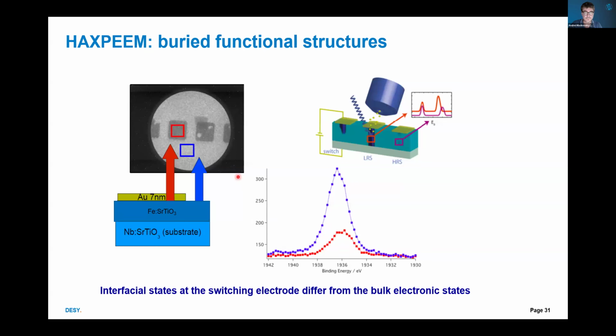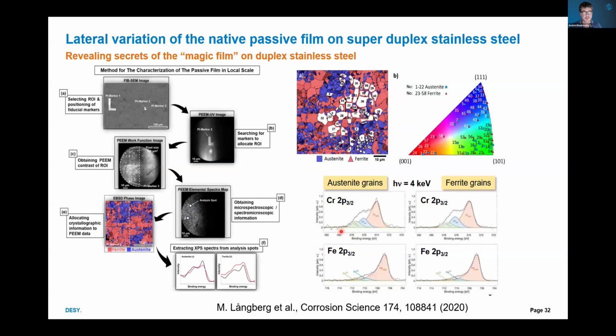Or you can also study ferroelectrics. You can see the pads clearly, and if there is an STO sample underneath the gold electrode, the red pad was switched, and the blue one is a bare substrate. You can localize them in the microscope, and then extract their spectral information. And you see that the interfacial states at the electrode are different from bulk electronic states. Also, you can study... Time is going. Yes, yes. So I'm wrapping up. Stainless steel, you can see different grains and also detect subtle variations in the grains.